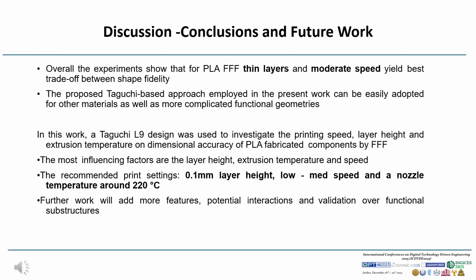We found that layer height is the dominant factor, followed by extrusion temperature and speed, and we recommend a parameter window of 0.1 mm layer height, low to moderate speeds, and nozzle temperature around 220. Future work will investigate additional parameters, possible interactions between them, and validation on more complex functional components.